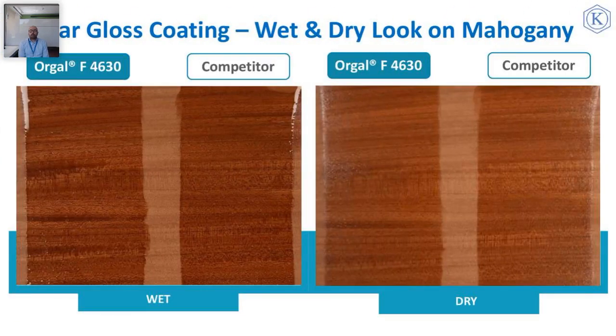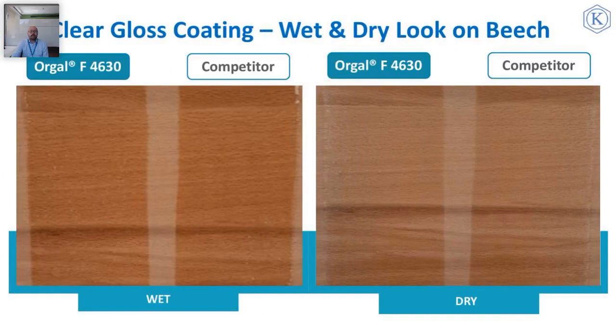Mahogany is another popular wood type which is used especially for assessment of wood forming and grain enhancement properties. Excellent wood forming property of Orgal F4630 is much more easily seen on this wood panel. The last tested wood was beech, which shows wood forming relatively less compared to previous wood types. Despite this fact, similar good wood wetting and grain enhancement performance was achieved.